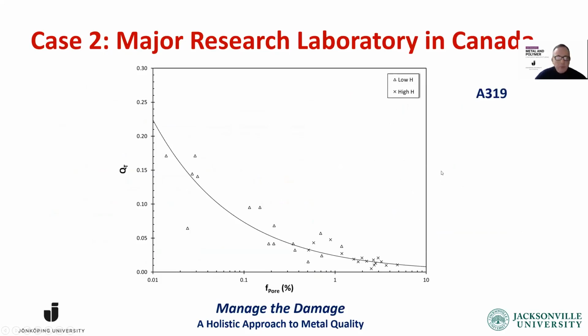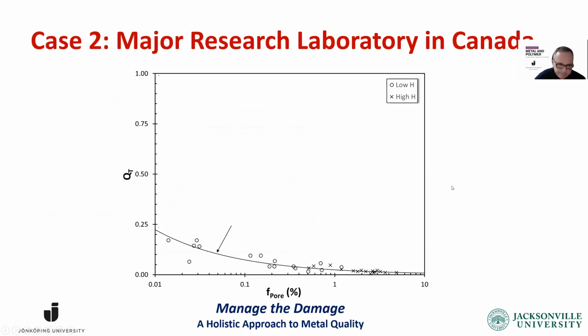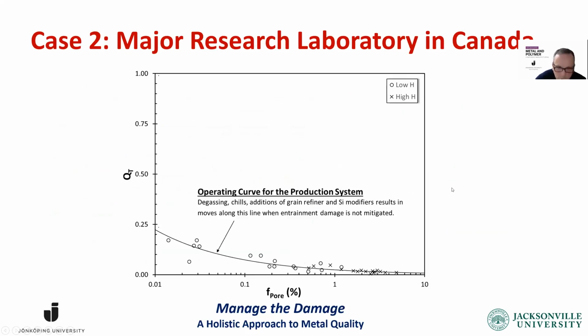Second case comes from a research laboratory in Canada, this 319 alloy. I took their data, plotted them, low hydrogen, high hydrogen, doesn't matter, it falls on the same curve. Here I plotted the pore volume percent versus quality index. What I did here is I zoomed in. Let's zoom out. When I zoom out, what do we see? This is the operating curve of the production system. So when we degas, all we do is we move on this curve. We go from left to right or right to left.